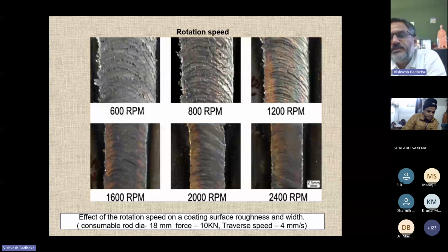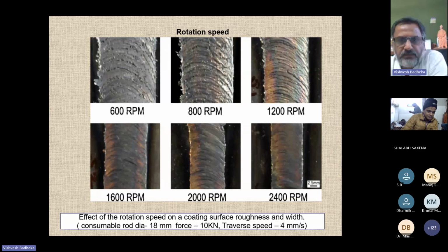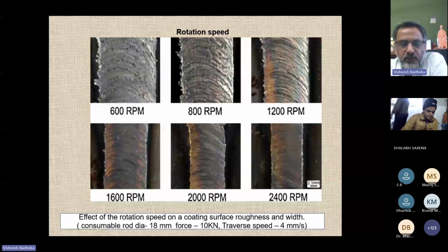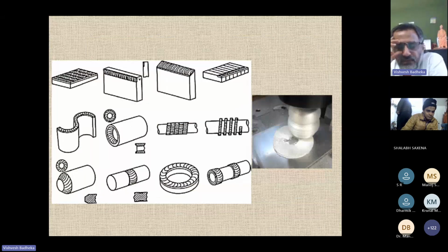the friction surfacing process. The more the RPM, the more the centrifugal force, and because of the higher centrifugal force, the material transfer efficiency from the rod to the substrate deteriorates. That is how the bead width is also decreasing with increasing RPM, and the finish is improving further. And as I mentioned, this process is not suitable for long length application.